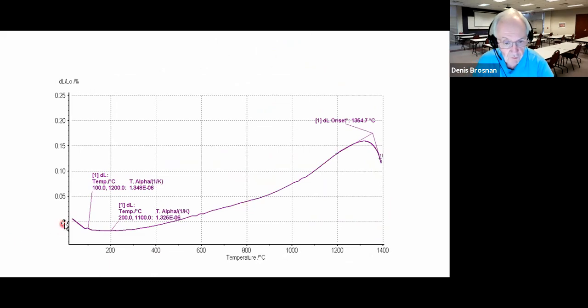Well, here's the thermal expansion coefficient, starting out with 0% expansion and heating up. Notice it didn't go up uniformly. All of a sudden it went down. The thermal expansion coefficient was negative. The reason for that is the anisotropic expansion of the cordierite crystals. So if you line up these crystals that you've created in firing of the talc, clay, and aluminum mixtures, then you'll get a dip in the thermal expansion on heating. And then in this particular cordierite, we had an inflection point of about 1365 degrees Celsius, and that's getting pretty close to the peritectic temperature. So that's where approximately this product was probably fired in this example.